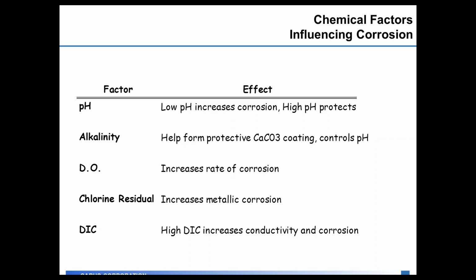Alkalinity is another thing that we look at. Alkalinity helps you form that calcium carbonate white coating in the distribution system. It also helps you control the pH by buffering the water so you don't see pH swings out in the distribution system as the water ages.